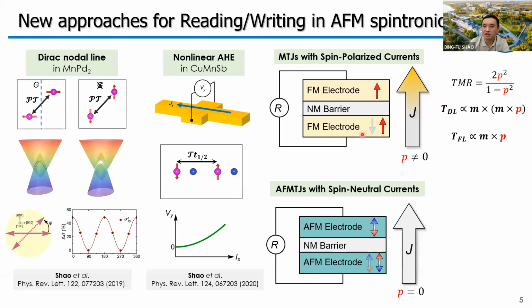It would be desirable if we can have a similar antiferromagnetic tunnel junction and use these methods for readout and write-in. However, the conventional understanding tells us these effects are all based on spin polarized currents, where the spin polarization P is finite. While in antiferromagnets, we usually have only a spin neutral current where P is 0. So it seems it's impossible to have a realistic antiferromagnetic tunnel junction with these effects.